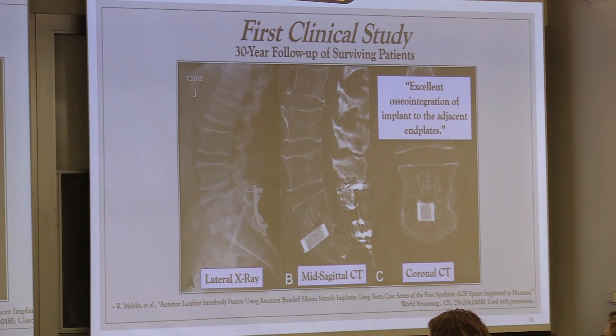Worked very well. In fact, the authors basically stated that the study, quote, confirmed that silicon nitride is biologically safe in the long term. Remember, this is a 30-year follow-up, with excellent osseointegration. So it works very well for that particular purpose.